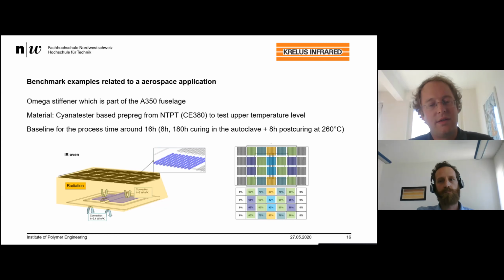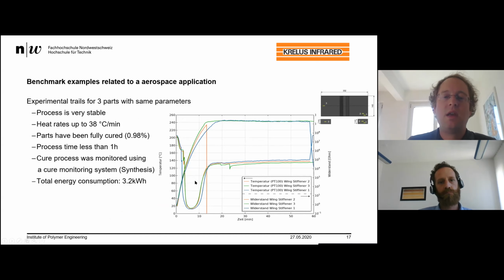So on the left side, the part is demonstrated, and on the right side you can see an upper view, and there you can see the power distribution which we apply in the heat field. And this power distribution was an outcome of our simulation coupled with an optimization approach. And so if we look now at the performance of the system, we can go up really fast to temperatures above 240.